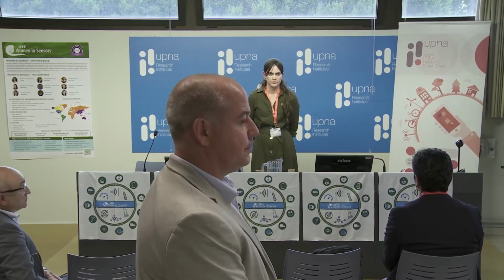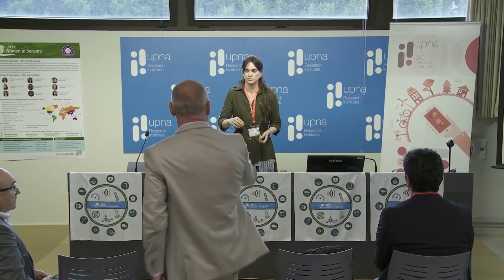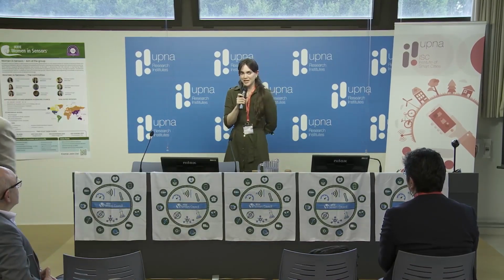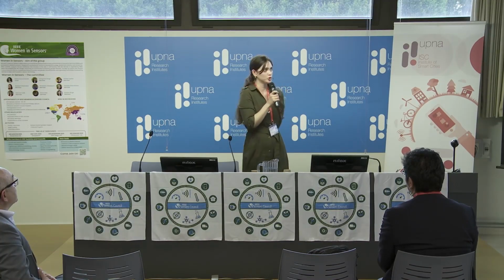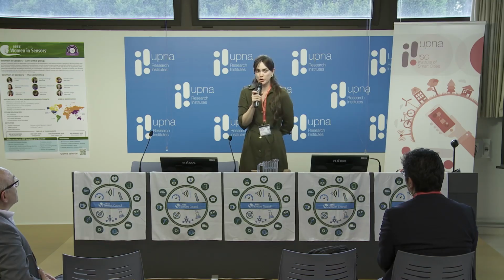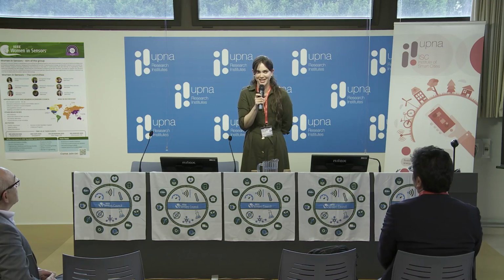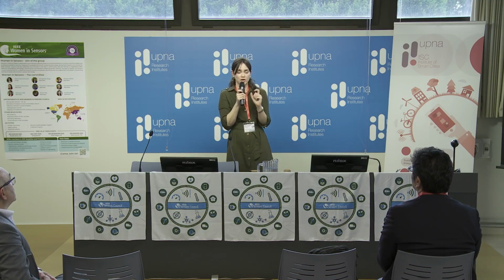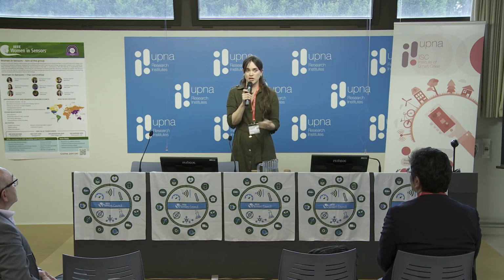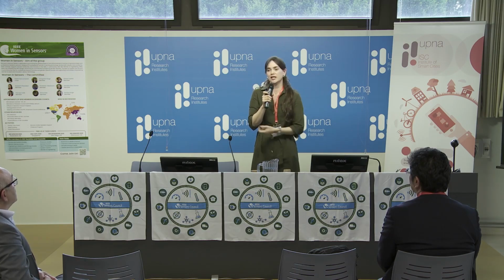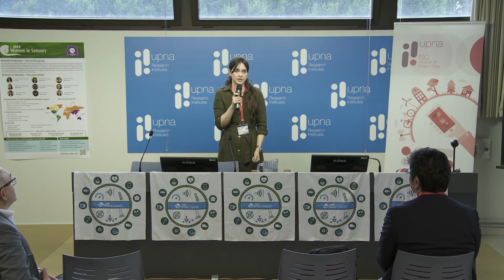Could you elaborate on the procedure you follow to determine this number of deposition cycles of the quantum dots? Thank you, Dairon. Well, in this work, we show the main representative results, but in fact, we made sensors with a number of layers from 5 to 100 layers. With a lower number of layers, the luminescent emission was not enough for the response, and with too many layers, the effect of self-quenching and scattering also makes it not work.